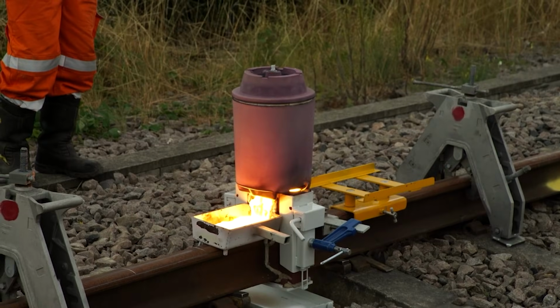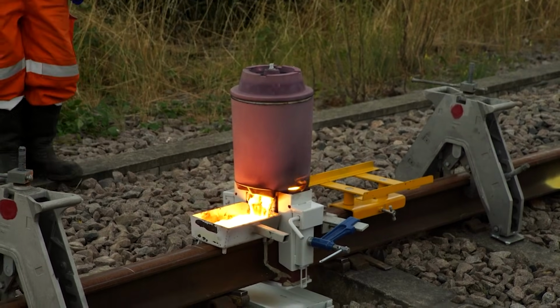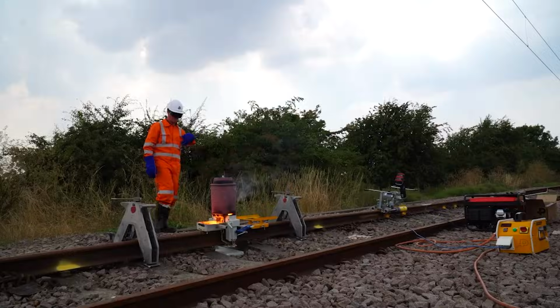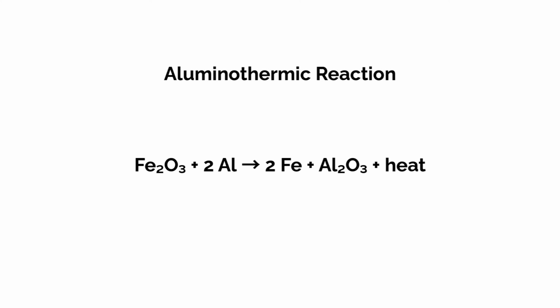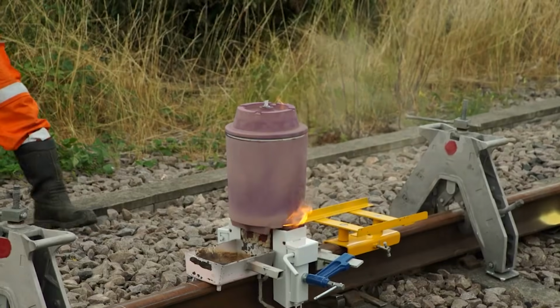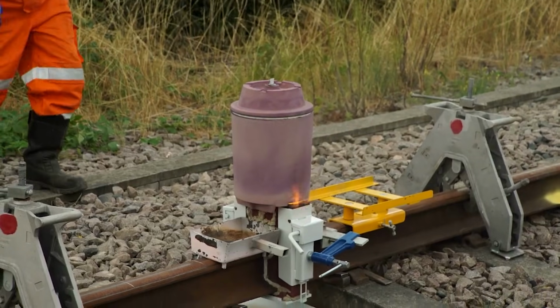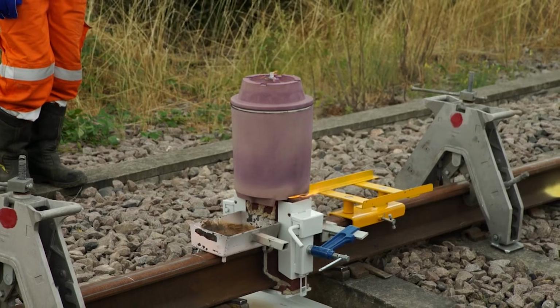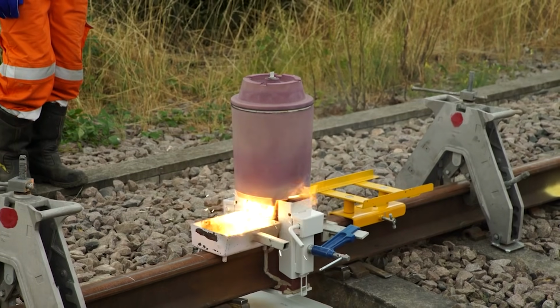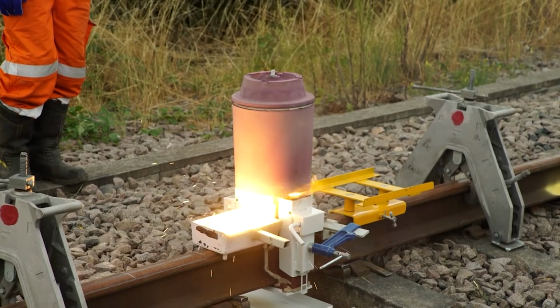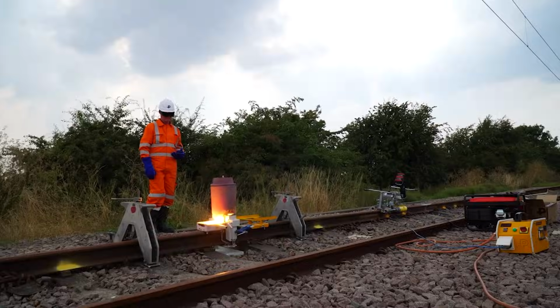A small ignition charge, often a magnesium ribbon strip or electric igniter, depending on the system, is lit by the welder. That heat starts the aluminothermic reaction, a redox process where aluminium steals oxygen from iron oxide. This reaction reads as iron oxide plus aluminium produces iron, aluminium oxide, and heat. The aluminium is oxidized, forming aluminium oxide, while the iron oxide is reduced, releasing molten iron and an enormous amount of heat. Temperatures reach about 2,500 degrees, hot enough to liquefy iron instantly.